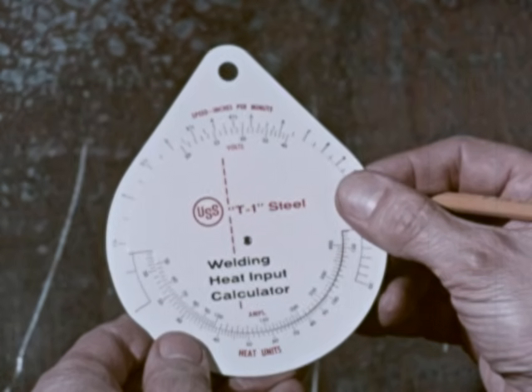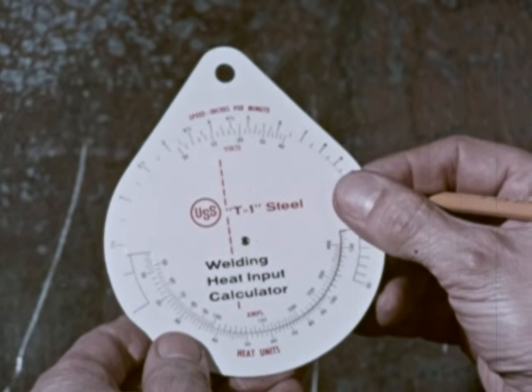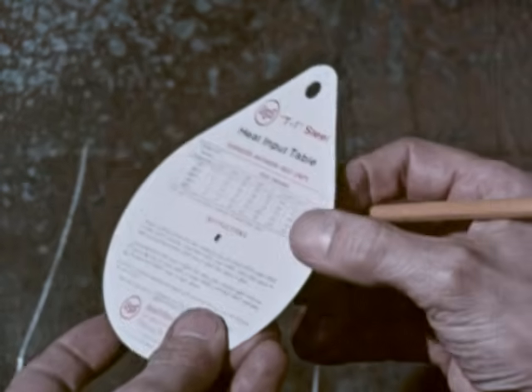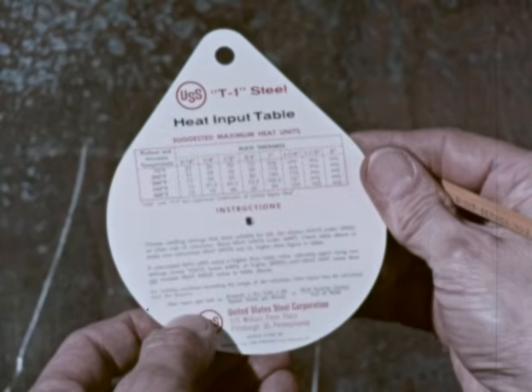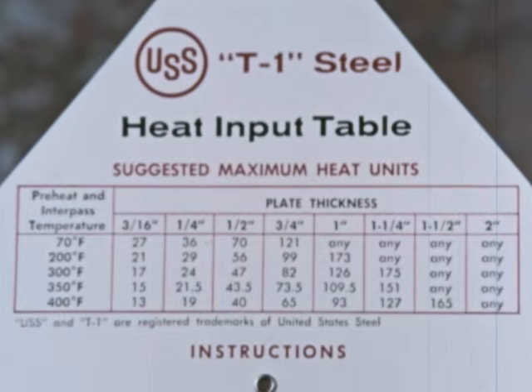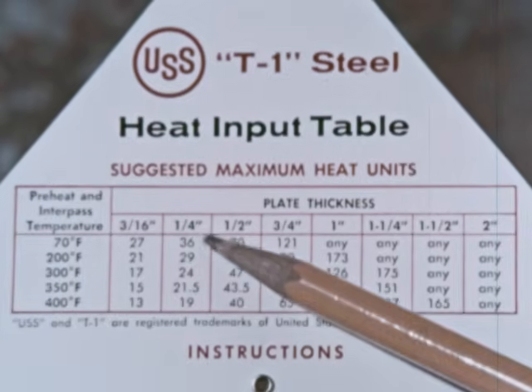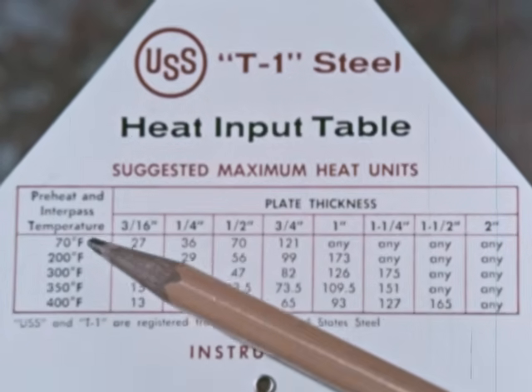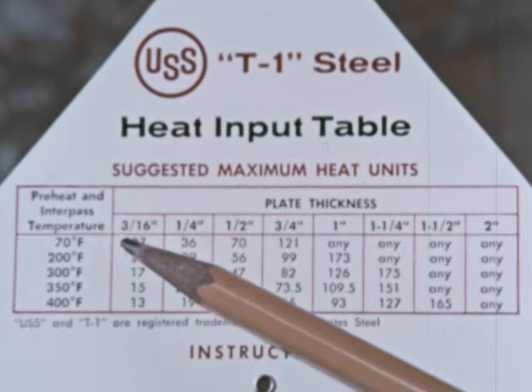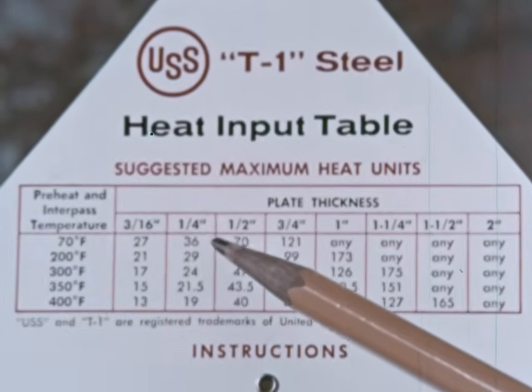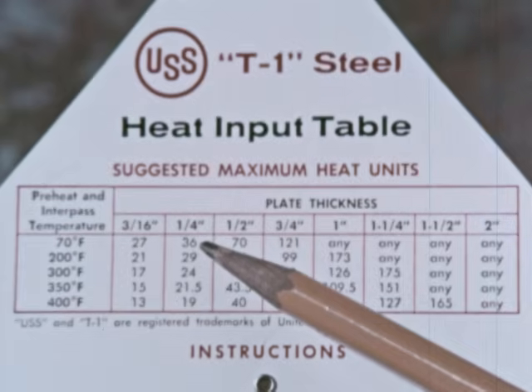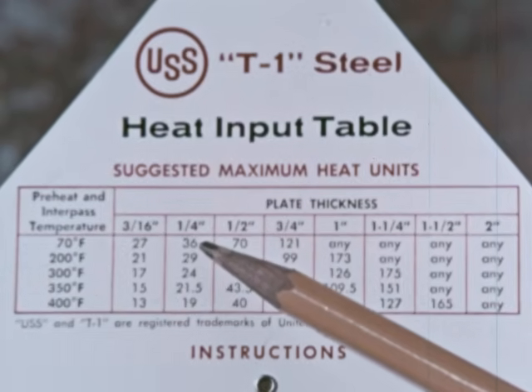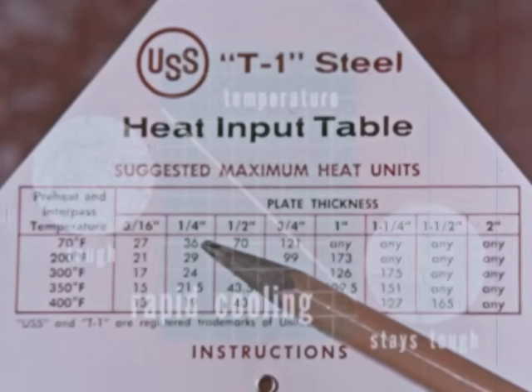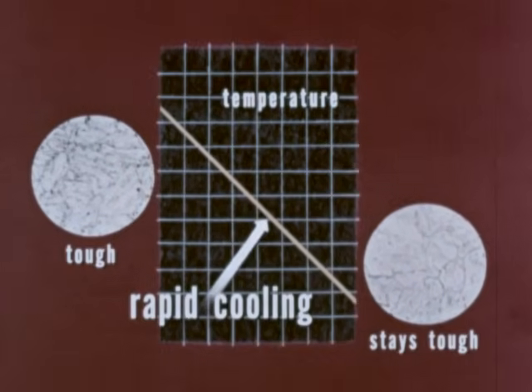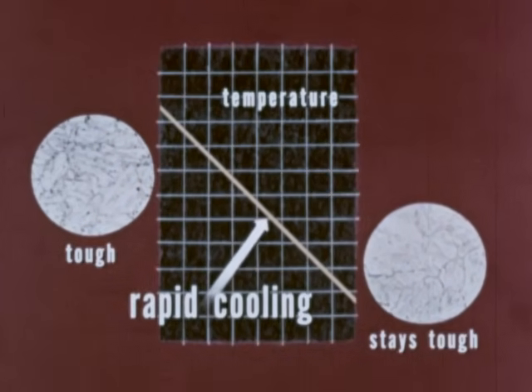How will you know that a specific heat input is within safe limits? This answer is on the other side, a heat input table with suggested maximum heat units. Say your plate thickness is a 1/4 inch. Its temperature, 70 degrees Fahrenheit before welding. In this case, 36 heat units are the suggested maximum. That is, with 36 heat units or less, we make possible the rapid cooling, which means a good, tough weld.